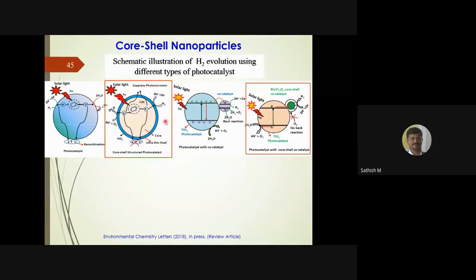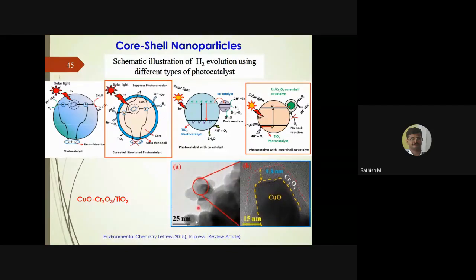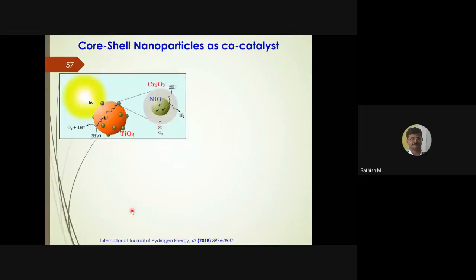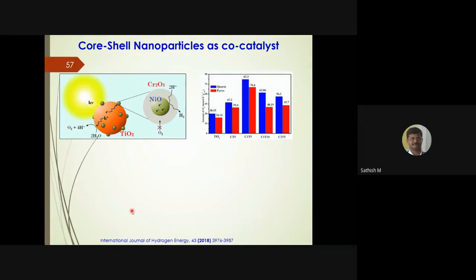So by having this, we made a different kind of catalyst system, like a core-shell system, where we find the core is active, but the core has some issues like a photocorrosive material. Then you could have some stable TiO2. One of the advantages of TiO2 is that it is a very stable system, so it will be very tolerant to all chemical environments. So that is one of the advantages why TiO2 is still active for various applications, particularly photocatalyst based applications.